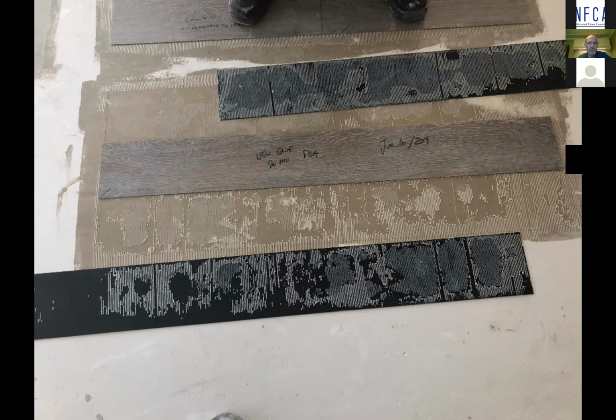And what you want to see here, you know, when we test floor coverings in the lab for performance standard, we're using a peel test machine that is all calibrated and it's bonded. We have a spot bond material, and it's hooked up to the machine, and the machine pulls up on it. Well, you can't necessarily do that on a job site. So what we're looking to identify here is when we pull on it, it's got to have some reasonably strong adhesive characteristics where it's a bit of a bear to pull it off the substrate. You can still get it off, but it's a bit of a bear to pull it off.